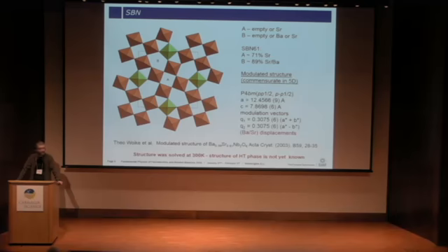Well, maybe, but to describe the crystallography of this stuff, you have to go to 5D space because it's a modulated structure with 2 extra dimensions needed to describe the modulations. So you see the literature data and how the structure was refined. The modulation was attributed mainly to the displacement of barium and strontium shared positions along the channels.